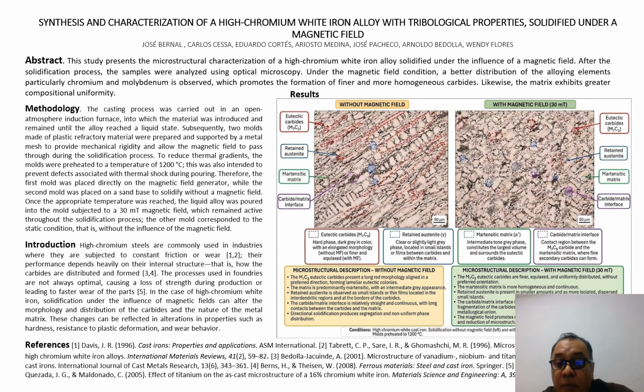Dispersed small islands. The carbide-matrix interface is more tortuous and fragmented due to the greater fragmentation of the carbides, increasing the contact area and favoring metallurgical union. The magnetic field promotes refinement, homogeneous distribution of carbides, and reduction of microstructural segregation.